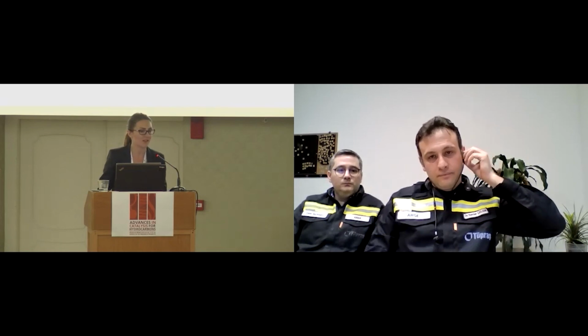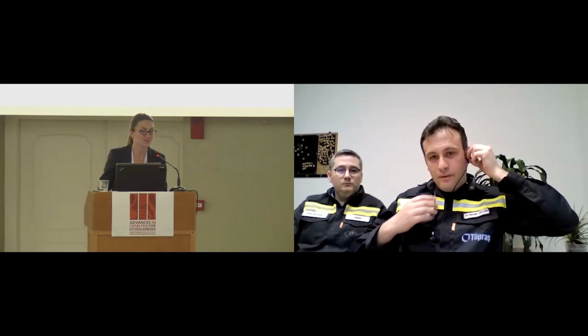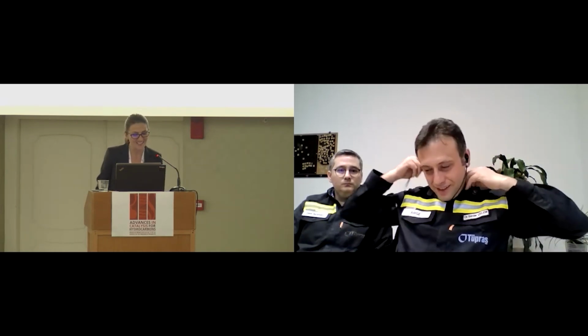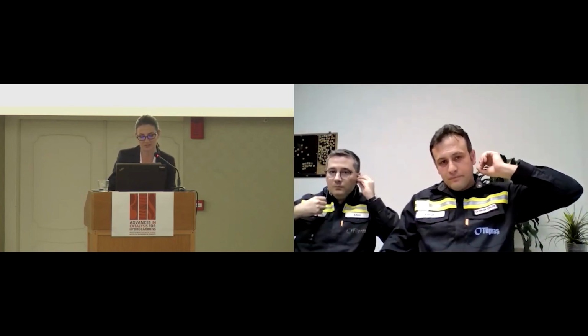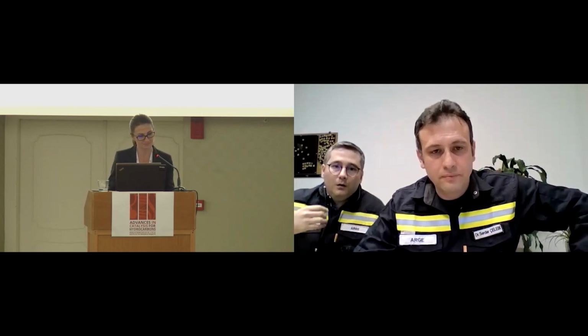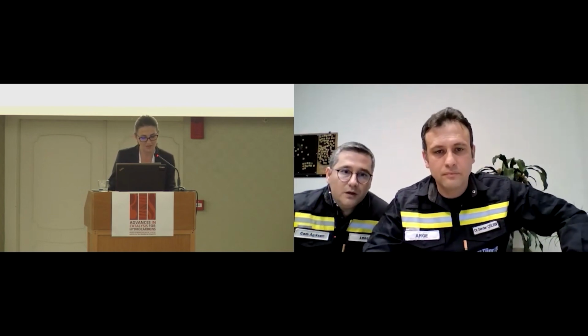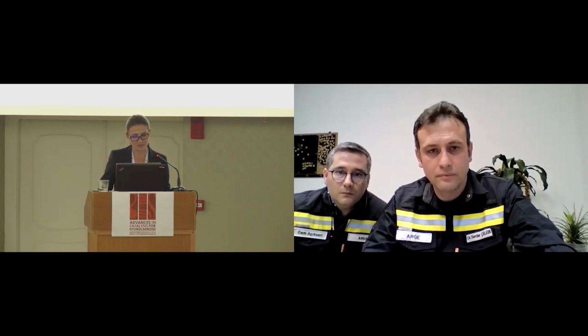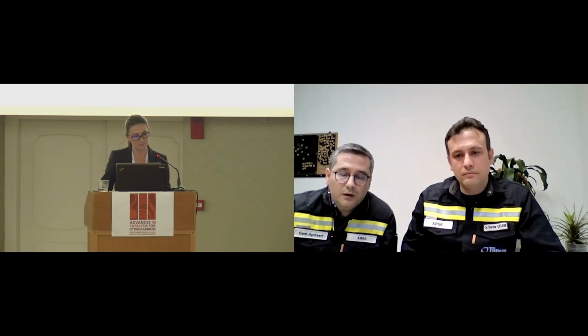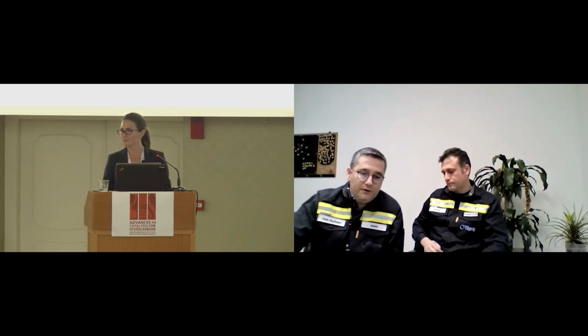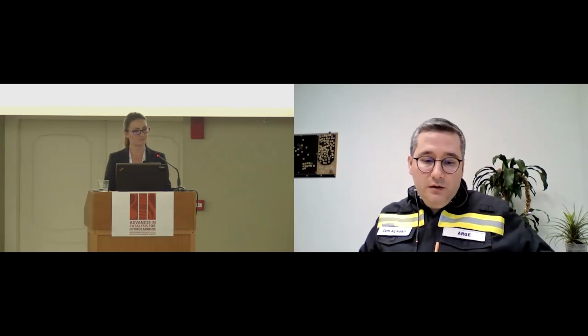And I think I have the last question for both of you this evening. Do you think that Pt weight can be decreased more for propane dehydrogenation reaction? Excuse me, could you repeat the question? Of course. Do you think that Pt weight can be decreased more for propane dehydrogenation reaction? I think so, because in industry we are using the platinum tin catalyst with a platinum ratio of around 0.5% by weight, or maybe lower than this ratio.